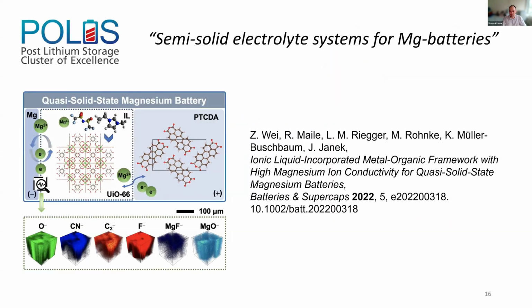In 2022, Jürgen Janek and co-workers started to incorporate the concept of a quasi-solid state electrolyte system based on a zirconium MOF, UiO-66, intrinsically functionalized with an ionic liquid in its pore interior. And they have utilized the semi-solid electrolyte system for a very challenging kind of battery system that is being researched in our post-lithium storage excellence cluster based on magnesium.